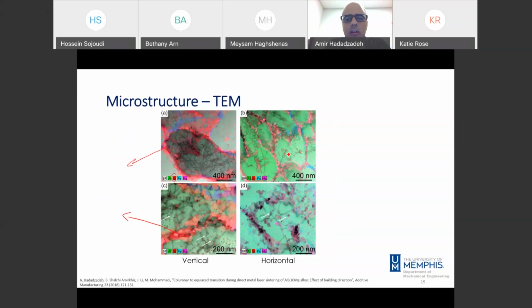The first one is the tiny nanoscale silicon particles. For example, here in this picture, in all of them, we can see many nano-sized silicon particles, and this scale bar is 400 nanometers. In addition to that, we see a network of dislocations. So these dark lines in the structure, in all of them, represent the dislocations.